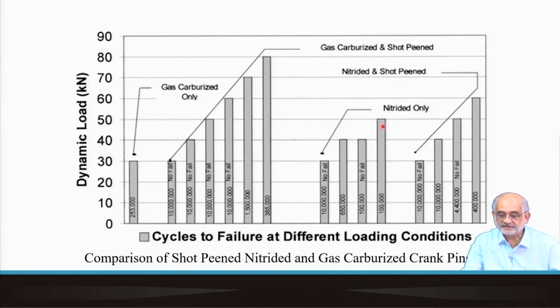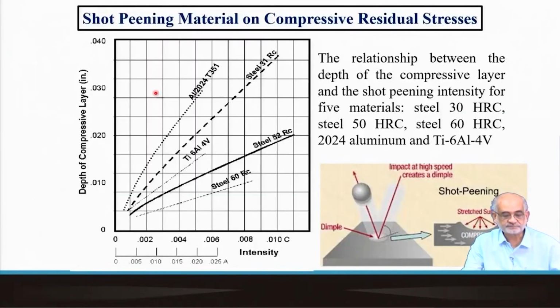And purely nitrided may also produce residual compressive stress and can show a certain fatigue life, but the life obviously is improved when it is not only nitrided but is also followed by shot peening. And as you can see, the number of cycles required for failure is much higher. So we have seen how it can also vary.